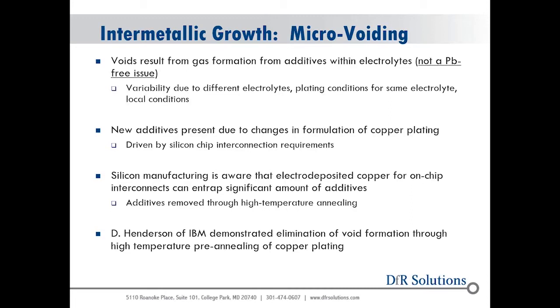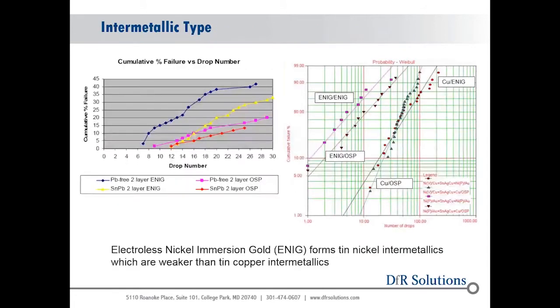but what happened was, during the lead-free transition, people were looking for reasons why lead-free boards were failing, and they did cross-sectioning and saw these microvoids, but then they did cross-sectioning on tin lead product and saw the same microvoids, so it wasn't really a function of lead-free. But again, any type of voids or things at the interface or in the intermetallics, again, you're reducing the cross-sectional area of the attach, you're increasing the stress, which can cause earlier failures during the shock event.